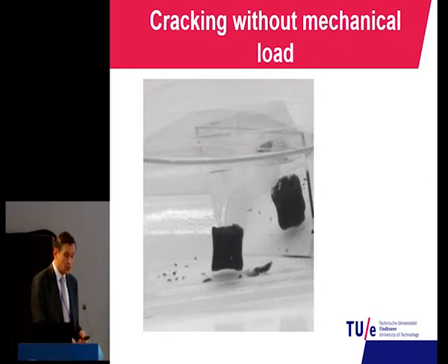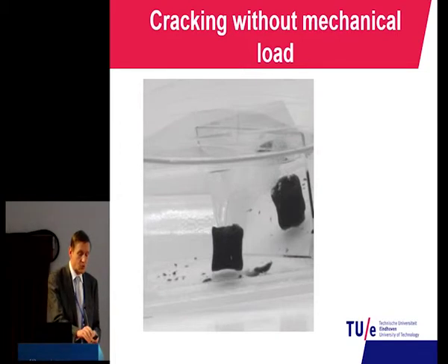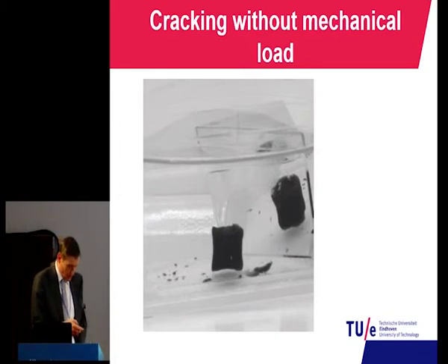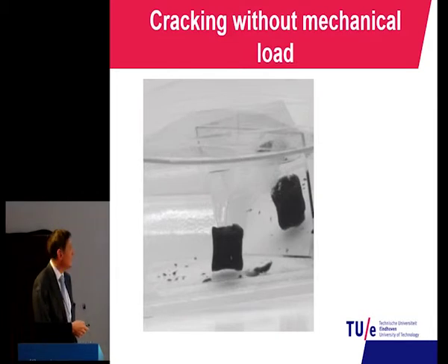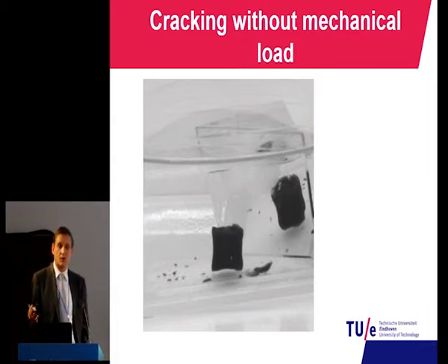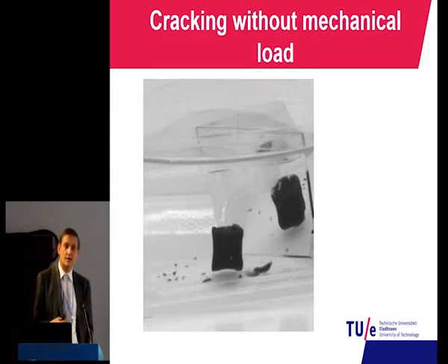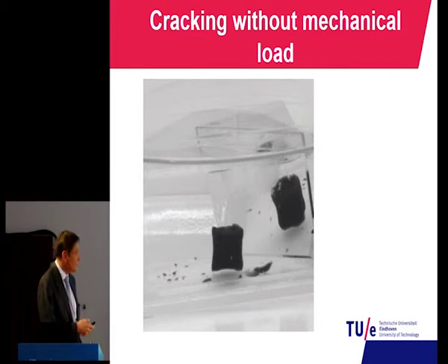If you move it from a high salt concentration to a low salt concentration, it starts swelling. While it is a perfectly symmetric structure, typically homogeneous and isotropic, you find that it develops surface instabilities. Why? Because the outside swells first, and the inside needs more time to swell. As it goes on, you see that a saddle shape develops.